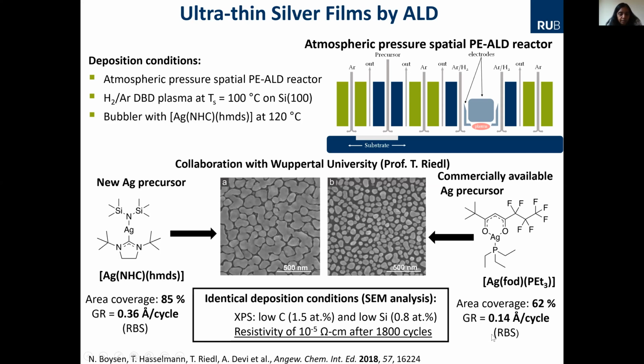And the growth rate was enhanced. So you have 0.14 angstrom per cycle, and in this case, you had 0.36 angstrom per cycle. So we found that the precursor with no oxygen, no fluorine, and no phosphorus has a better coverage at lower thickness. You have well-connected layers, and then the resistivity was of the order of 10 to the minus 5 ohm centimeter after 1,800 cycles. So this was, I would say, a big success for our group, because that was the first report where we could show that you can have very thin layers of silver which are conducting, and one can come down further with the thickness to make it more transparent. And that's ongoing research where we're looking for molecules or process parameters where we can scale it down further.